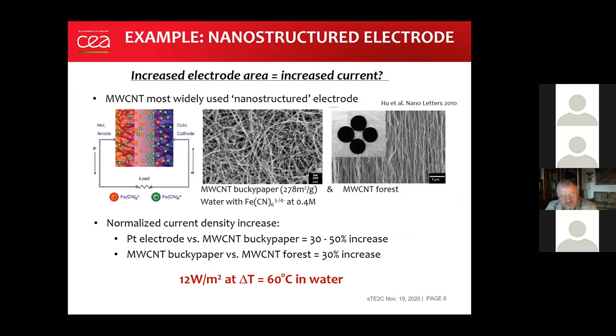So just to give you a couple of examples, the most advanced research in liquid thermoelectrics right now is the use of nanostructured electrodes. So here are examples: the use of multi-wall carbon nanotubes, either in the form of Bucky paper or aligned in a carbon nanotube forest. By using the Bucky paper, several groups were able to show that the power output from a thermal cell can be improved by 30 to 50%. And by further aligning these carbon nanotubes, you can again increase the power output by 30%. At the moment, the record power output from a liquid thermoelectric cell is about 12 watts per meter squared at a delta T of 60 degrees. Of course, this was achieved in water.